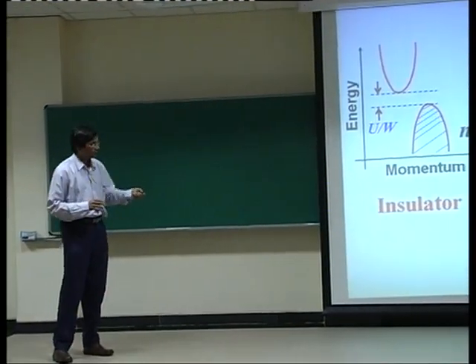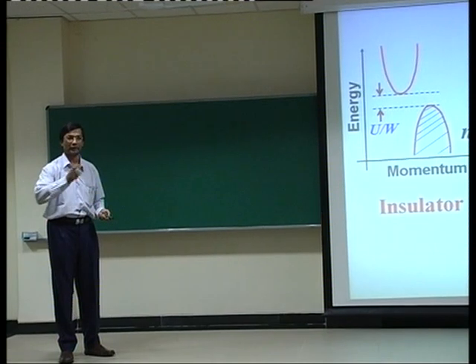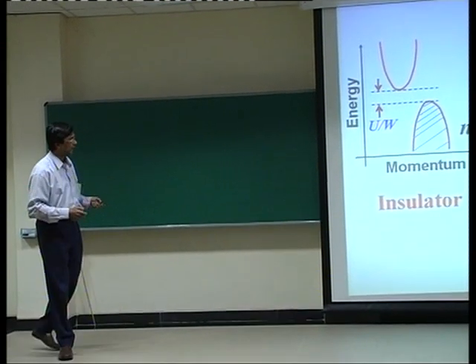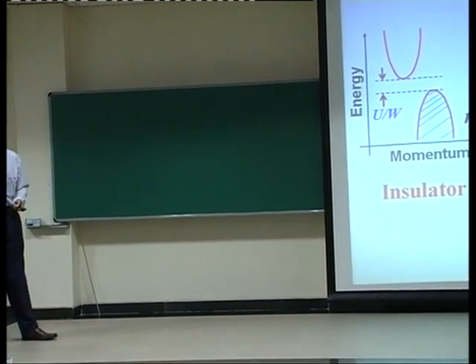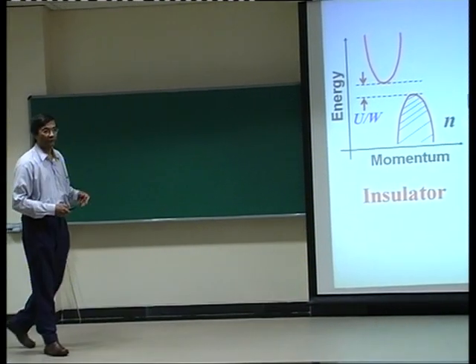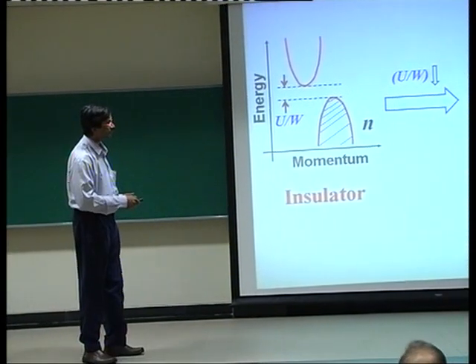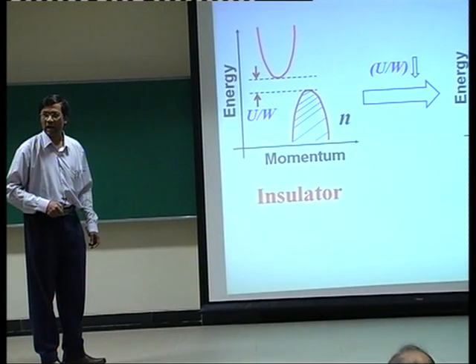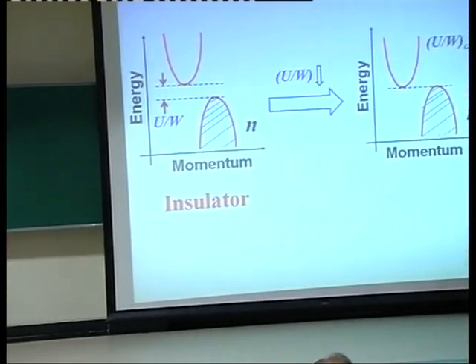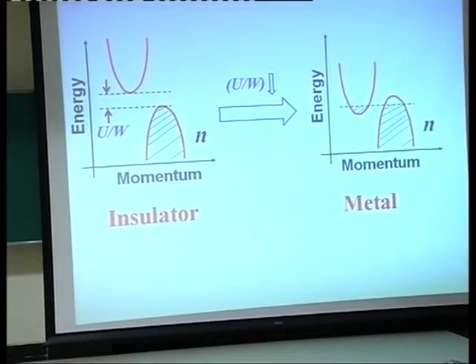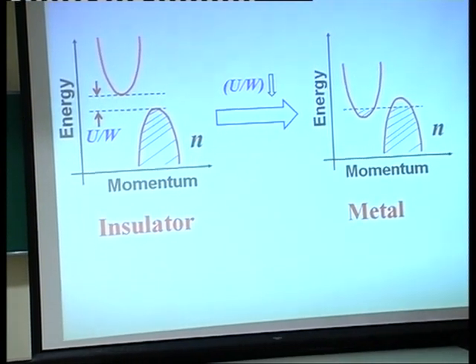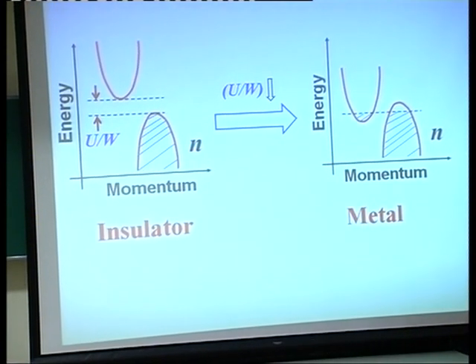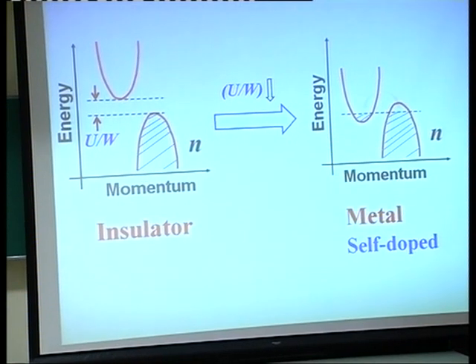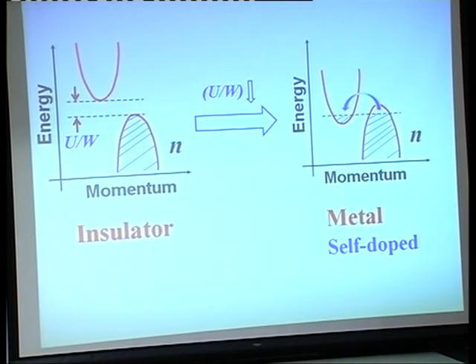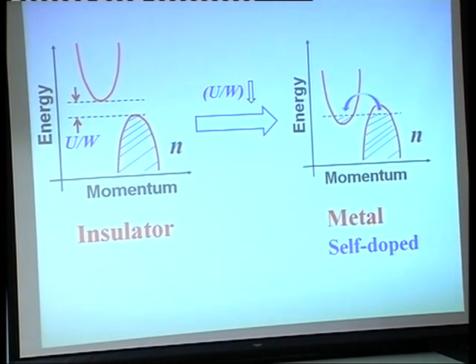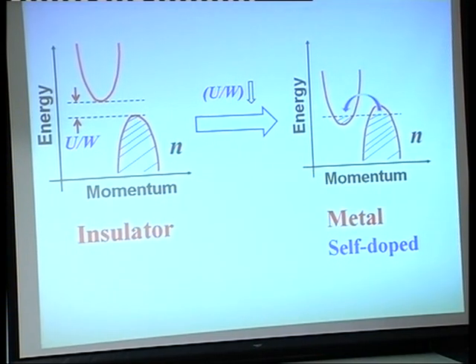So if I now, starting from this insulator, slowly decrease the Coulomb interaction strength or increase the W as you like, so U by W, if I go on decreasing, slowly I'll reach a critical value of U by W where these two pieces will begin to overlap with each other. And beyond that critical value, if I decrease the U by W any further, there will of course be a metal state. And this metal state happens because the electrons from this part would flow into this part. So it's a self-doped metal, where one part of the band structure dopes the other part of the band structure.